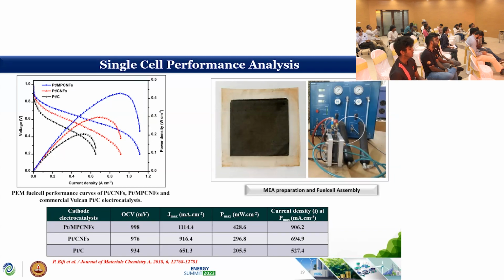The current density also was following a similar trend. Which means that the usage of mesoporous carbon nanofibers could effectively improve the performance of proton exchange membrane fuel cells. We understand that there are many factors in that, but of course, the introduction of nitrogen-doped sites, the mesoporous structure, and the uniform deposition of platinum nanoparticles have effectively contributed towards enhancement of the performance.